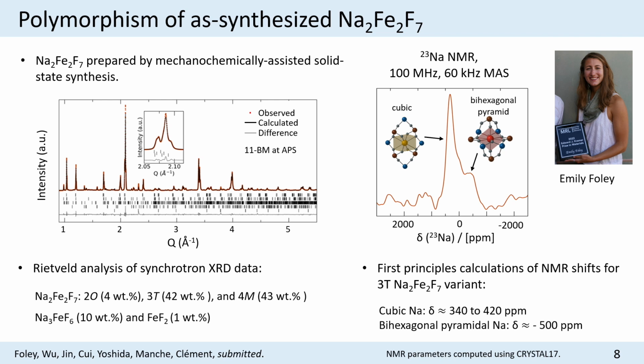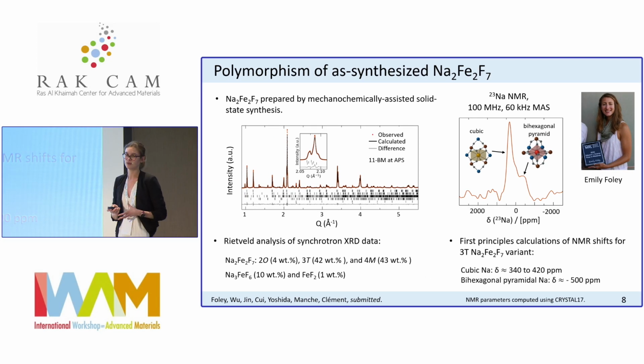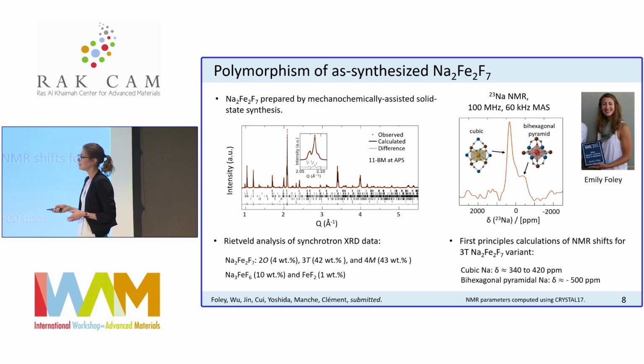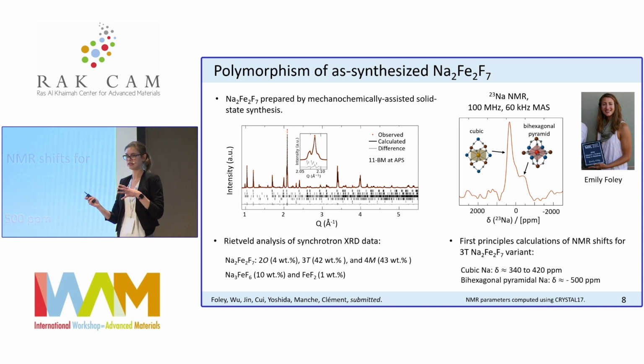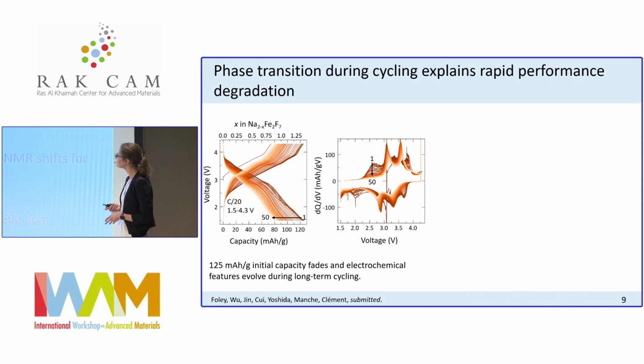And what we find here is that we have mainly two environments, and we can assign these environments using first principles calculations again, but this is now first principles calculations of paramagnetic NMR properties. This main peak corresponds to the cubic sodium in this material, and the lower intensity peak is sodium in a bihexagonal pyramidal site. But you can see that there are some shoulders as well. So there seems to be more than 2 sodium sites, which could be explained by the fact that we have more than one polymorph. So we have slightly different environments in these polymorphs too.